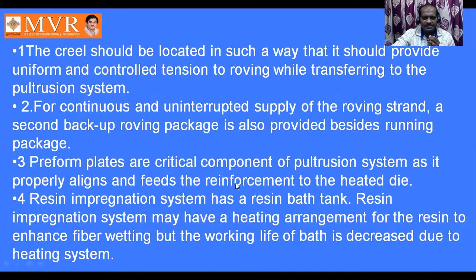The resin impregnation system can be a resin bath tank. The resin impregnation system may have a heating arrangement for the resin to enhance fiber wetting, but the working life of the bath is decreased due to the heating system. See, after the fibers pass through the preform plates, they are going to be dipped into the resin bath.